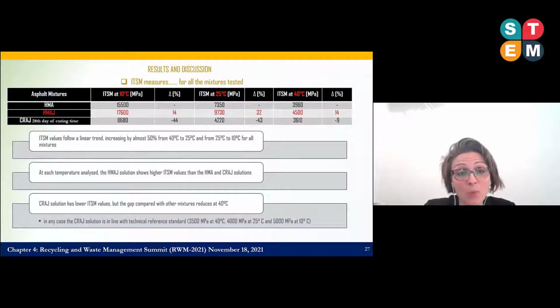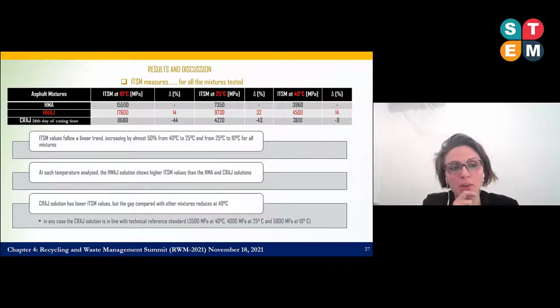Regarding the stiffness modulus of all mixtures, the maximum value is reached, as I said, for the hot mix with jet grouting waste. In particular, we can see that the maximum value is reached, of course, when the temperature is reduced, but the gap between values for traditional hot mix asphalt and hot mix asphalt using jet grouting waste, or cold recycling of old milled asphalt mixture with jet grouting waste, occurred at the 28th day, reduced at 40 degrees, and this is important for us.